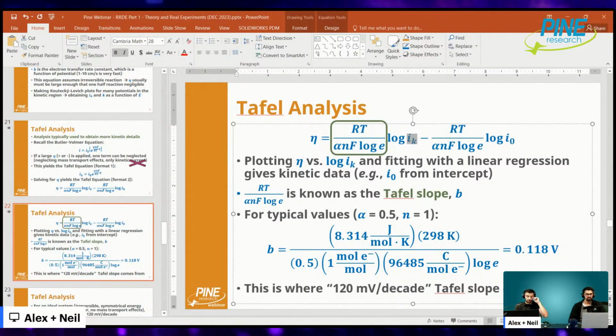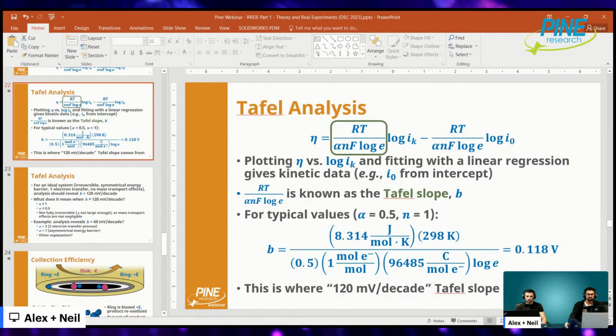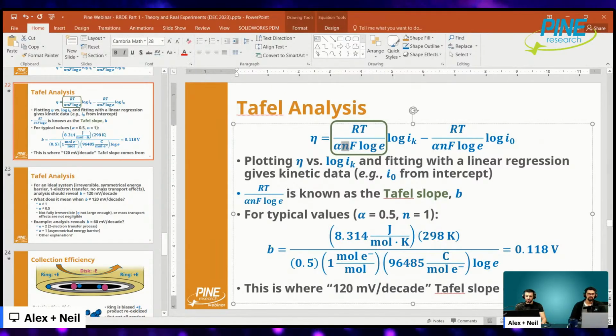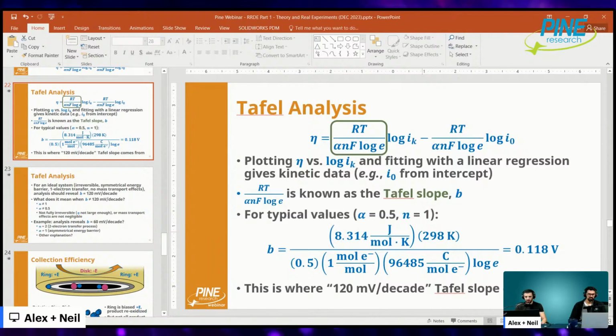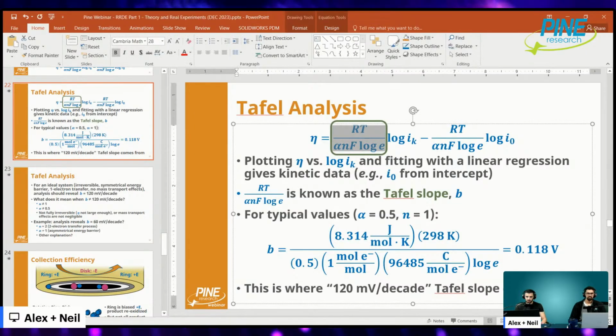However, if you are confident that your current is 100% kinetic current, then the interpretation or translation, or whatever terminology you want to use, is usually in terms of n. A lot of times the Tafel slope equates to a way in which to interrogate the number of electrons of your reaction that's occurring, because it is a factor of 120. So in a perfect irreversible one electron transfer process, numerically this Tafel slope, R times T at room temperature, alpha with a perfectly symmetrical energy barrier, and one electron transferred, the Tafel slope is 118, basically 120 millivolts per decade of current. So this number shows up a lot. That's where this comes from. It's the calculation of a sort of ideal Tafel slope.